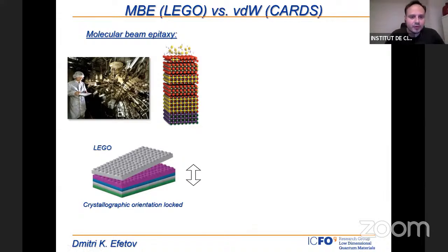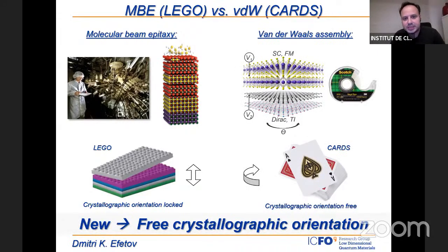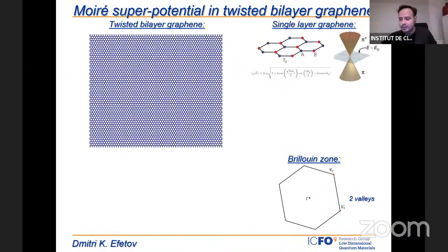material species. The problem with molecular beam epitaxy is, however, that each grown atomic layer inherits the crystallographic orientation of the previous atomic layer. So basically, the twist angle is locked into place, and really we can compare it with Lego, where you really lock layers into place. And this is really different here with these van der Waals materials, because we don't start with atomic species and single atoms, but we start with already well-formed two-dimensional crystals. And that really means that we can now really rotate these layers with an arbitrary angle, and we are not locked anymore to the crystallographic orientations. And this really is the enabling property which allows us now to perform these Moiré heterostructures.